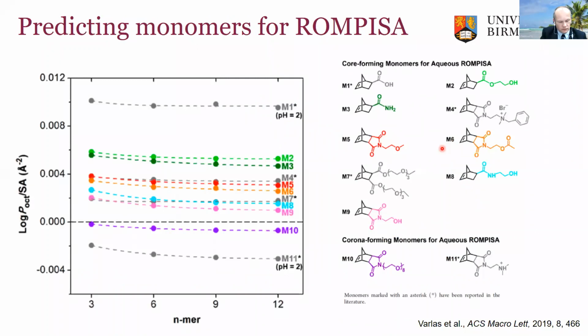Our initial papers were in RAFT PISA, but we also were able to apply it very successfully for ROMP PISA, so that we can actually draw a monomer that we might want to make and look at how it changes as we grow. As you see, these are relatively small oligomers, but we can determine the hydrophilicity or hydrophobicity and the increase in hydrophilicity or hydrophobicity as the polymer grows. Rather than make the monomer and try to see if it works, we can get a good sense of whether we think it might work based on the change in hydrophobicity or hydrophilicity as the chain grows. We showed this last year for ROMP PISA, and this is what we've been using to identify monomers that will undergo ROMP PISA.